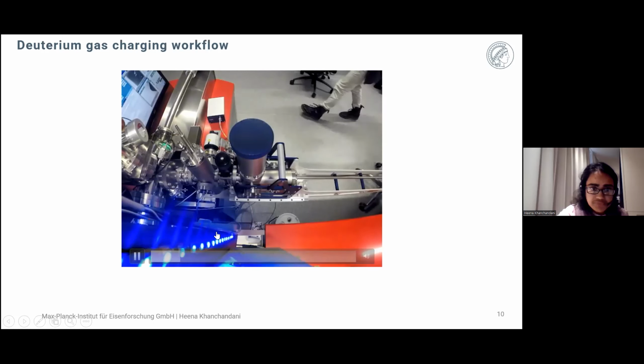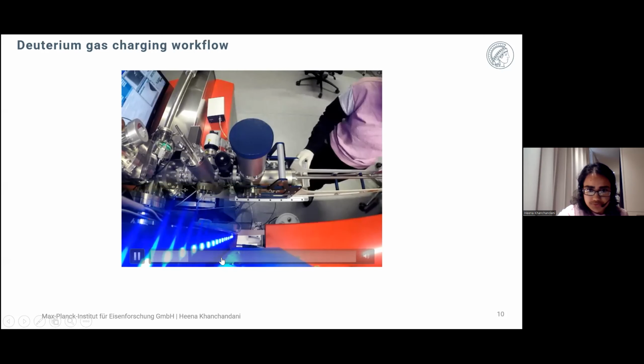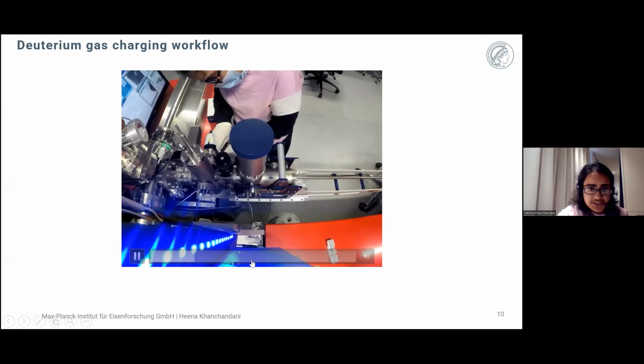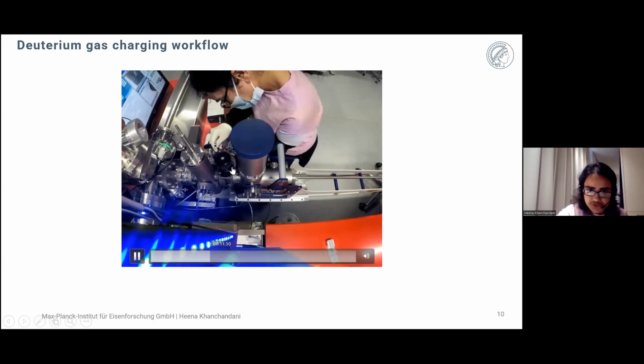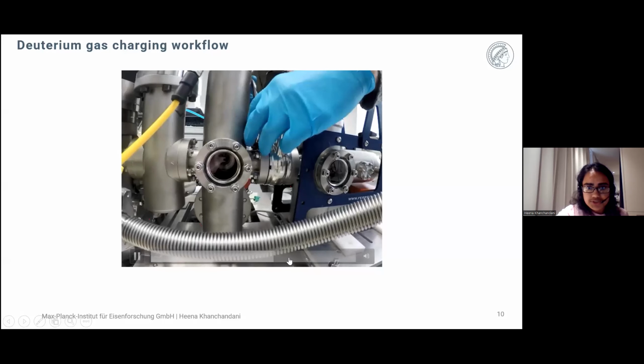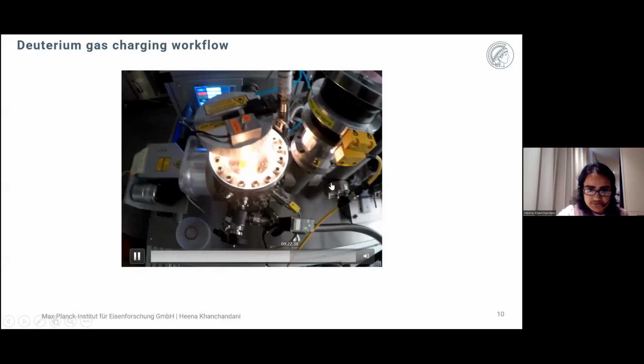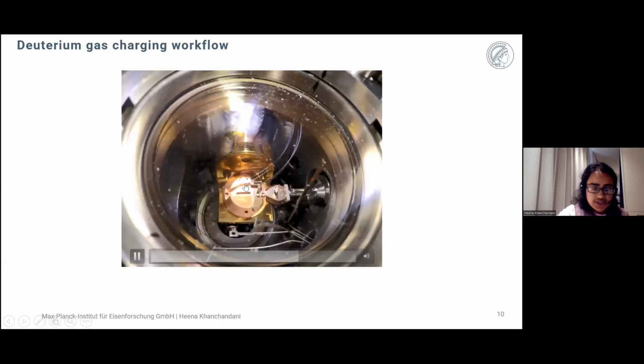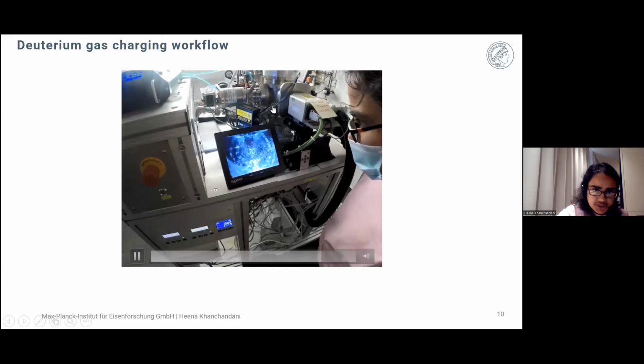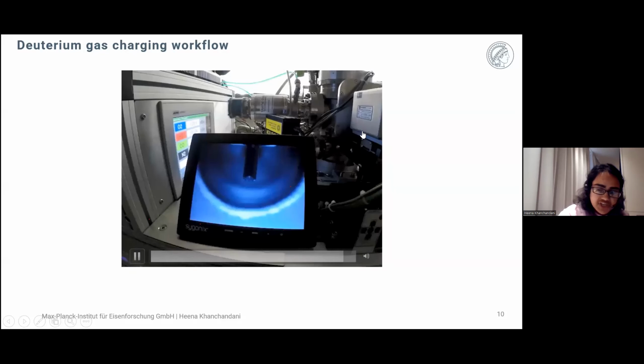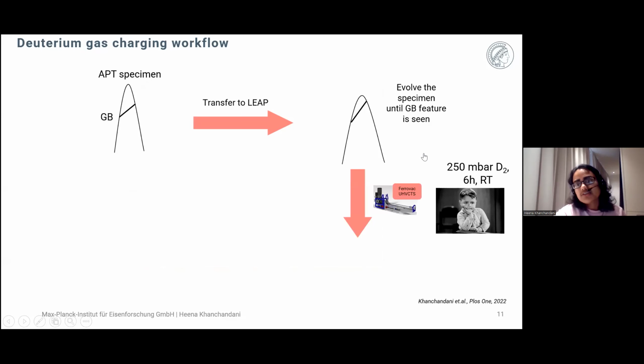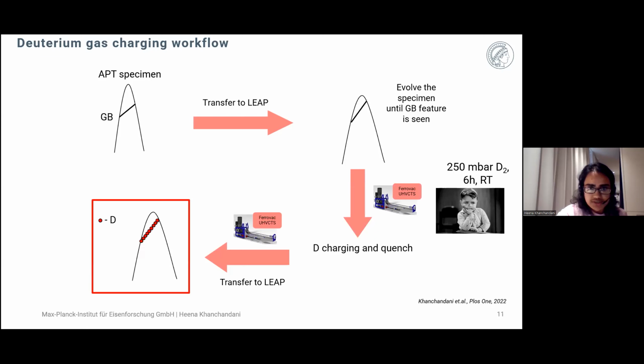In this, the sample is already pre-analyzed up to the grain boundary, and then it is transferred to this suitcase at the atom probe. And then this suitcase is detached from the atom probe, and it is connected to the reactor hub module. And then we transfer the sample from the suitcase into the reaction chamber. Then deuterium gas is introduced into the chamber, and then we start the charging. After this, we wait for some time. For instance, in this case, we perform the deuterium charging for 6 hours at room temperature. And after the charging, it was quenched in the suitcase, and then it was transferred through the suitcase to the atom probe for further analysis.